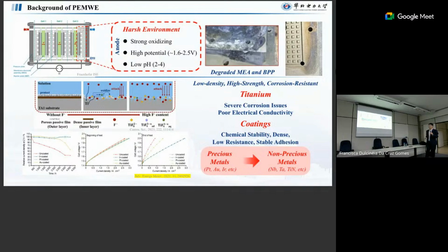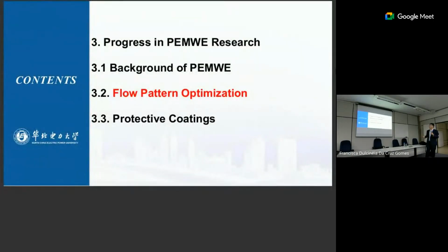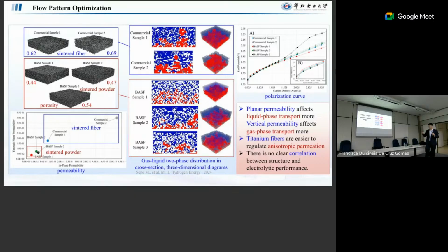And the second thing is to use cheaper coatings, because at the moment people normally use platinum, gold, and iridium, and we try to replace them with niobium, tantalum, and titanium nitride, for example. So that's another method to reduce the cost. Here I go very fast. For example, here we have fibers, and here we have sintered powders. The good thing is when we use fibers, we can put the fibers together to make a felt. And for this one, we have a lot of powders, which we can sinter to get a porous medium.